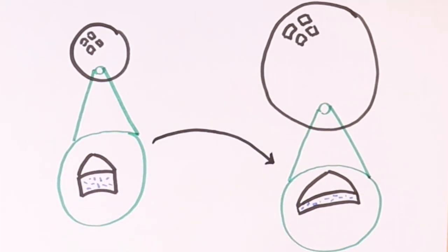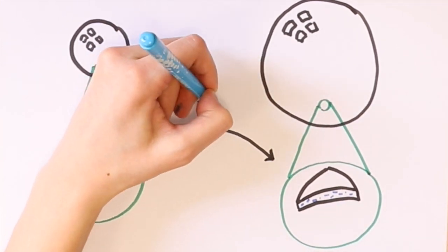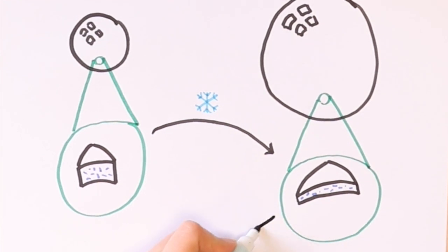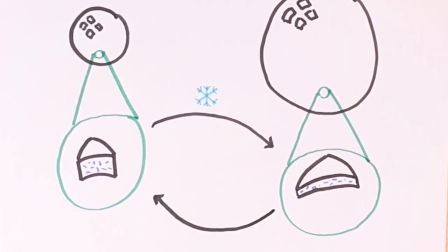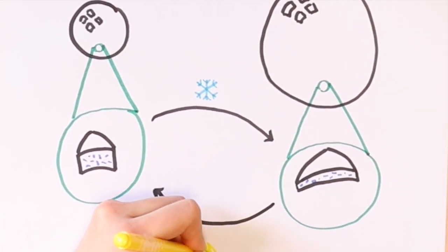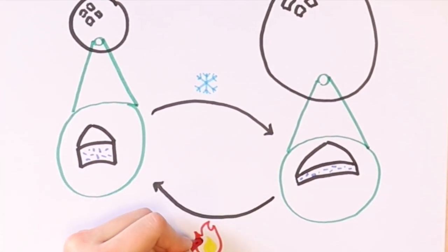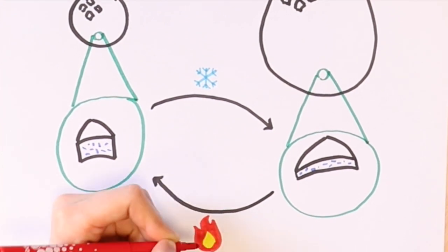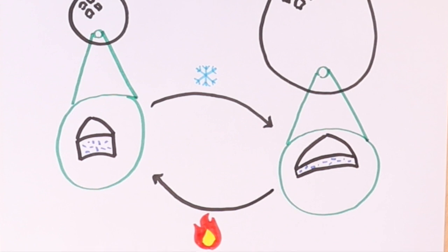What makes our liquid crystal rubber shell a bit different from the party balloon is that it can actually do this order change on its own, without us inflating or deflating it once we have prepared it. All we need to do is cool or heat it. If we cool, we get the anti-ordered negative order parameter state, and if we heat, we get the random zero order parameter state. And because this is a rubber, the shape has to change between thin and wide and thick and short.